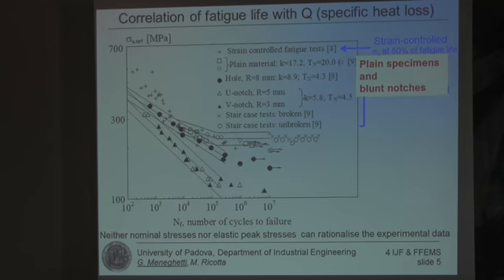Now, we have recently summarized a great number of experimental results of fatigue tests conducted on plain and bluntly notched specimens made of a stainless steel material. It is a 304 low carbon steel. Either strain-controlled fatigue tests or stress-controlled fatigue tests are reported here. We tested bluntly notched specimens, of course, with notch effects, which are not accounted for by the nominal net section stress amplitude.